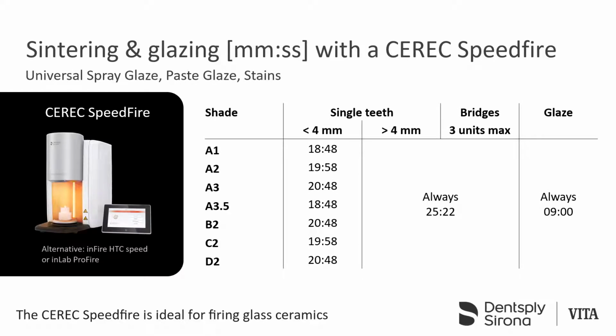The CEREC Speedfire is ideal for firing glass ceramics such as CEREC Tessera, but also for sintering zirconium oxide ceramics such as the CEREC MTL Zirconia. The table above indicates the sintering and glaze firing times for CEREC MTL Zirconia in a CEREC Speedfire.